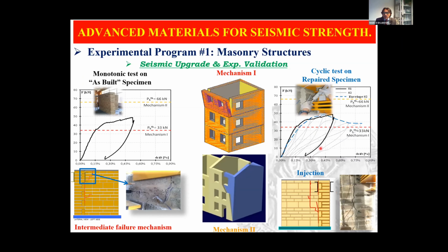Then we repaired it and we did a cyclic test in order to evaluate the effect of cyclic action as actually happens in case of a seismic event. And you can see the blue curve is the envelope of the cyclic test. And here you can see the crack pattern with a clear, very clear mechanism 2, which is the composite